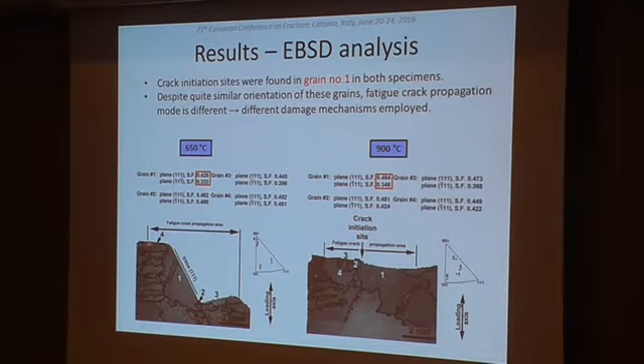In this case, we were also able to ensure that the crack is really propagating along slip planes of type 111. So this type, as you will see further, is really crystallographic dependent, this stage 1 mode.